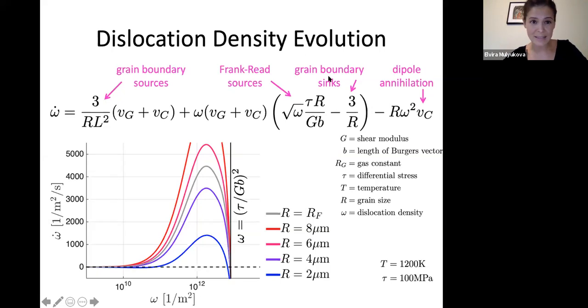Grain boundary sinks, again, is just as dislocations would merge onto a grain boundary, and that goes as grain boundary density, and the dipole annihilation. Dipole annihilation depends on the efficiency of climb because it requires exchange of atoms. It strongly depends on dislocation density because it dictates the probability of one dislocation of one sign encountering another dislocation of the opposite sign. Another thing that dictates the probability of them interacting with each other is the lifetime of a dislocation within the grain, which is dictated by how long it takes for a dislocation to traverse that grain in order to interact with a dislocation of the opposite sign. So this is where the dependence on grain size comes in.